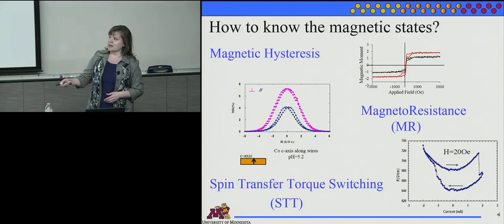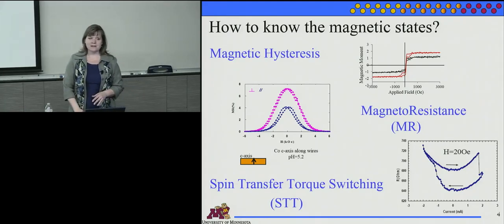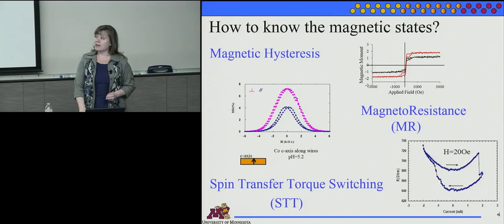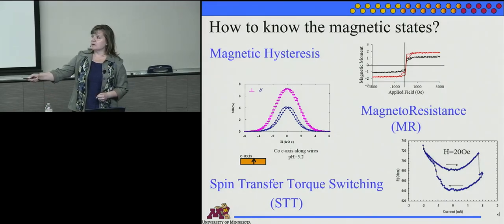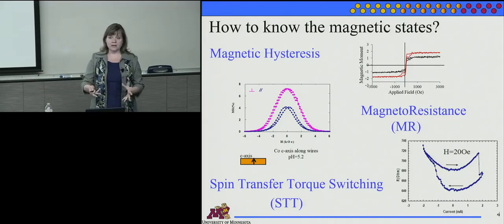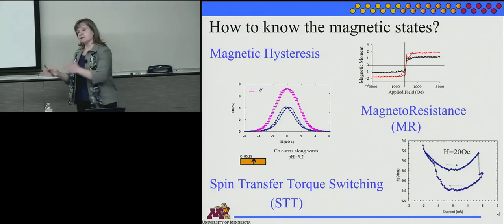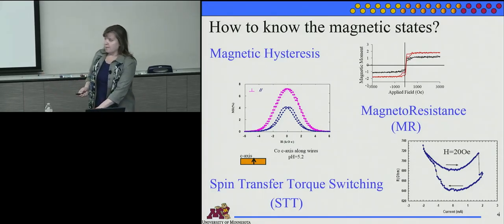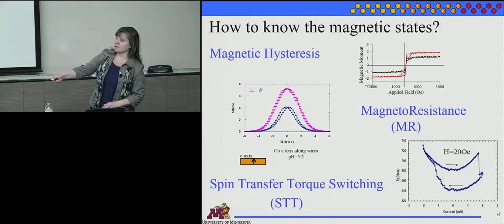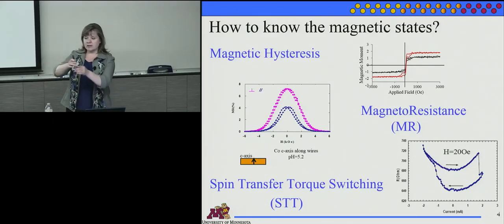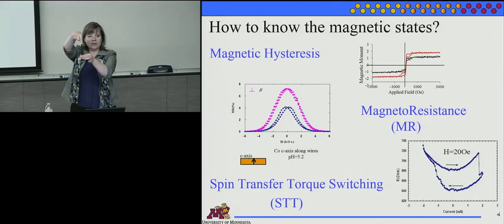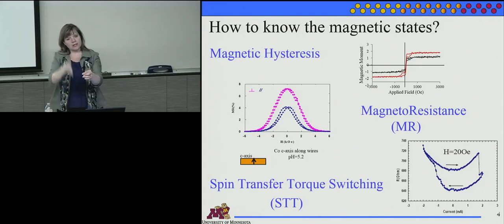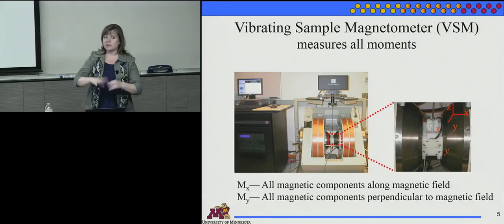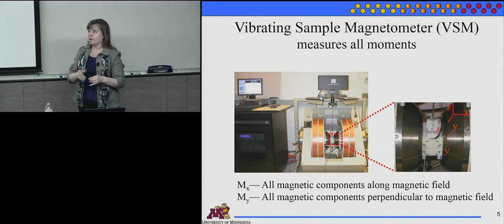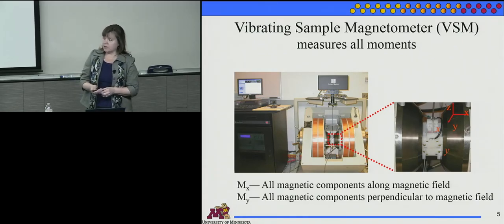You have already learned a lot about this, but I share this with some audiences that are students that might not already know anything about magnetism. And of course, you know that a magnetic hysteresis is going to pick up the entire sample, all the magnetic moment as it points in the direction that you're measuring it. Whereas magnetoresistance and spin transfer torque switching, if this is a nanowire, you're applying a voltage from the top to the bottom and therefore running a current through it. So you're measuring more directionality along the wires as opposed to the entire sample and everything going on all at once. And so just what do those two things look like?